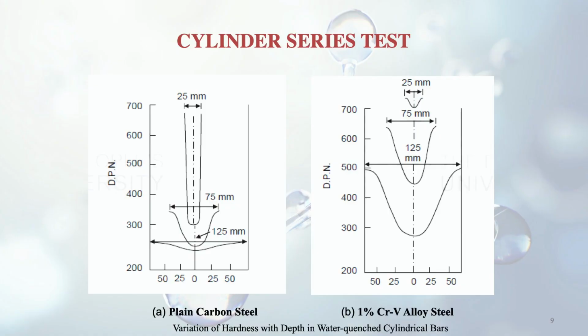The first figure is for plain carbon steel, which I have described to you, and the second one is for 1% chromium vanadium alloy steel. You can see a difference in the second figure: at 500 diamond pyramid hardness number, a 125 millimeter cylinder diameter hardness can be achieved, whereas in the first figure it was only at a hardness level of 250. So the chromium vanadium alloy steel gives better hardness.